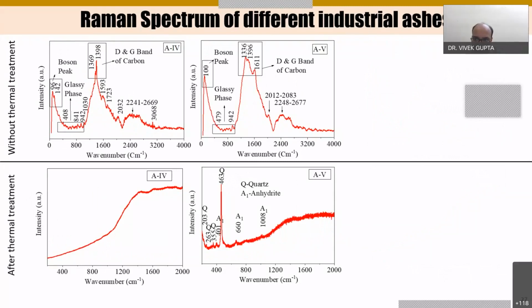We can also say in another manner that due to the high anhydrite component, we are able to identify those in the spectra. So ultimately, due to the presence of inherent minerals, the reactivity of A5 and A3 ash is high, and the same we have observed through the lime reactivity test.